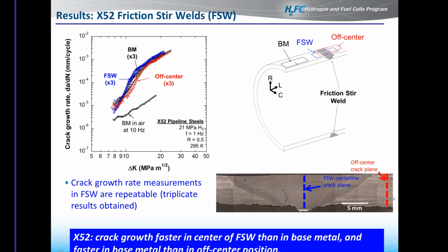The results of these, first of all, the base metal in air shows very similar trends to what we saw with the X65, a very linear response. And we also see hydrogen accelerated fatigue crack growth in this X52 pipe. Of the 3 areas, the friction stir weld had a slightly higher crack growth rate than the base metal, which is slightly higher than the off-center region. And once again, we saw very good reproducibility or repeatability among triplicate tests.